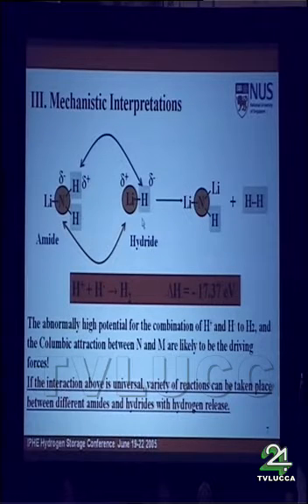Let me use lithium imide and lithium hydride, the interaction between these two compounds, as an example. You can say normally alkali metal imides are commonly used deprotonating reagents in organic synthesis. Nitrogen in imide possesses negative charge, and it will exert Coulombic potential on cations. In this case, it's lithium ions. At the same time, hydrogen in imide and hydrogen in hydride possess opposite charge. And the union of the hydrogen with different charge gives very high potential. Thus, we think the chemical driving forces could be both of them: the electrical attraction between nitrogen and cations and the high combination potential for the hydrogen.